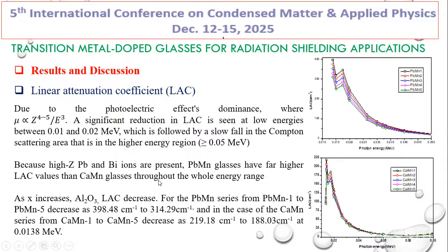The cause is the same thing, Z, the atomic number, which is high for lead and bismuth. So initially, compared to calcium, the glasses having lead and bismuth show high linear attenuation coefficient values. The values are given here. For the LAC of lead, it is 398.48 and it decreases to 314. Whereas for calcium, it is 290. 398 is the maximum value and calcium is 290. But lead is absorbing more, attenuating more radiation when compared to calcium, sir.